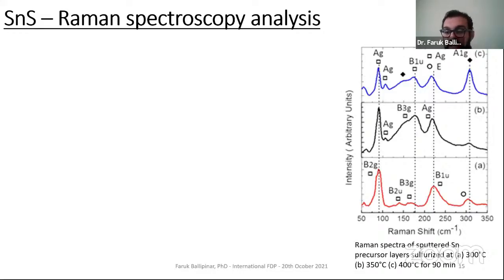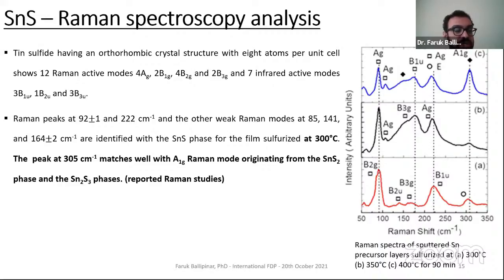Raman spectroscopy is a kind of light scattering technique that basically gives an idea about phase identification as well. According to theoretical papers from the literature, tin sulfide has 12 Raman active modes and 7 infrared active modes. These theoretical results were published in 1975. It is almost the main reference for the Raman analysis of tin sulfide material, and that analysis shows the peak around 300 matches well with secondary phases.